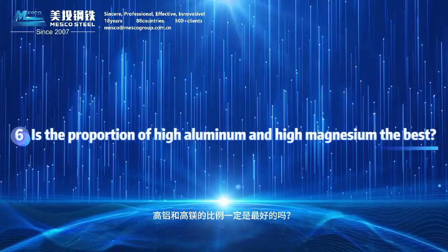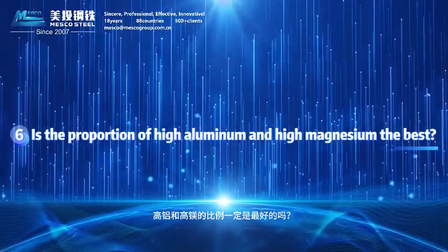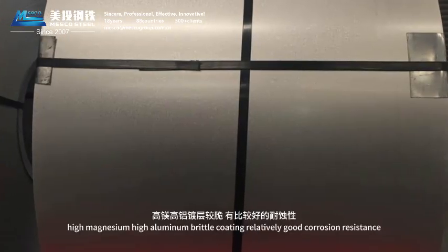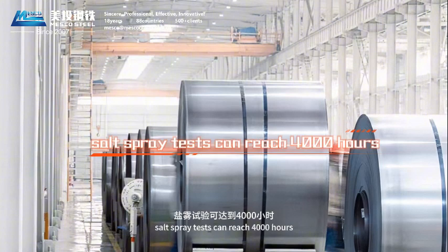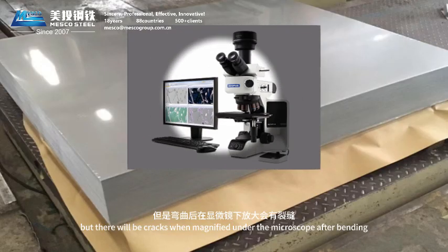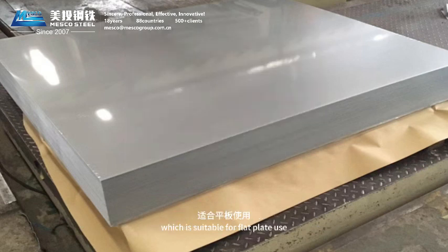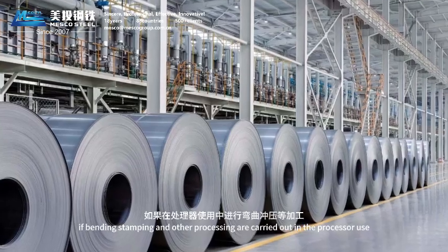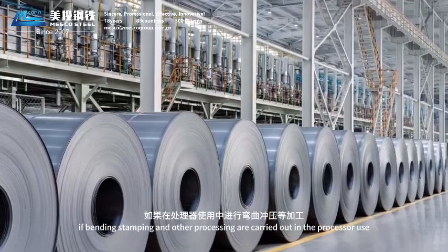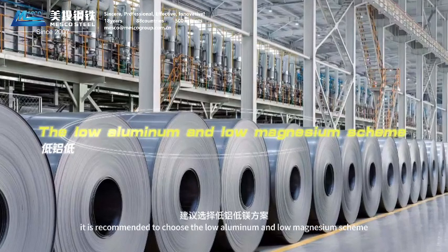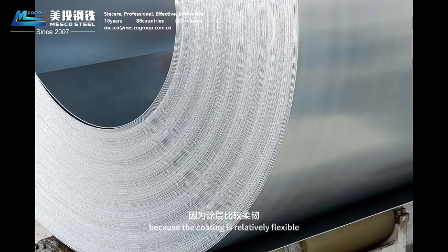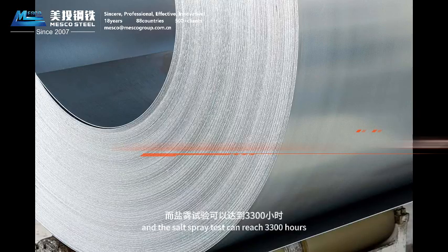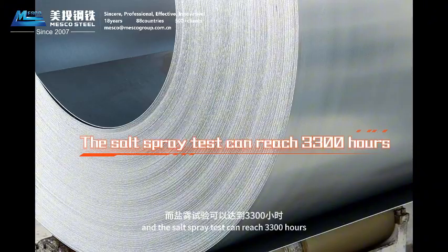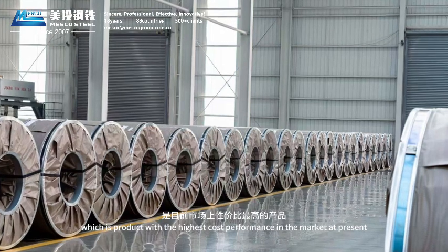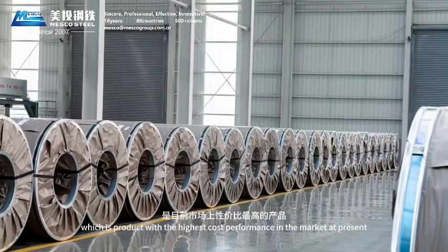Is the proportion of high aluminum and high magnesium the best? With high magnesium and high aluminum, the coating is brittle, with relatively good corrosion resistance, and it can rank first in the salt spray test. But there will be cracks when magnified under the microscope after bending, so it is suitable for flat plate use. If bending, stamping and other processing are carried out in the process of use, it is recommended to choose the low aluminum and low magnesium scheme, because the coating is relatively flexible, and it can rank second in the salt spray test, which is the product with the highest cost performance in the market at present.